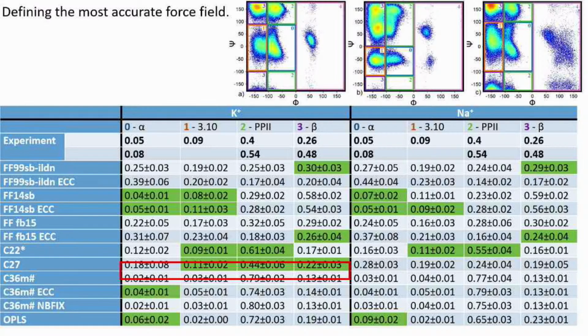But we can see that the fraction of alpha helical conformations here is higher than it should be, and it's a very well known problem of CHARMM 27. In the newer force field, CHARMM 36, developers tried to solve this problem, and you can see that the number of alpha helical structures is much lower in the case of CHARMM 36. But the population of other conformations was changed too. So at this time, for these systems, CHARMM 27 looks like the most appropriate force field to use.